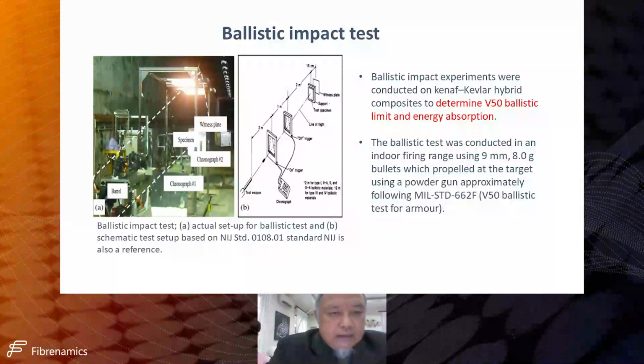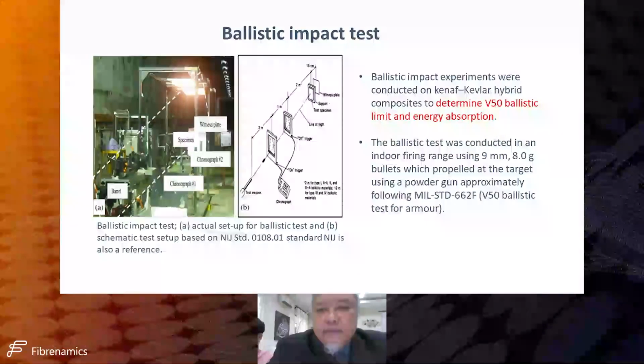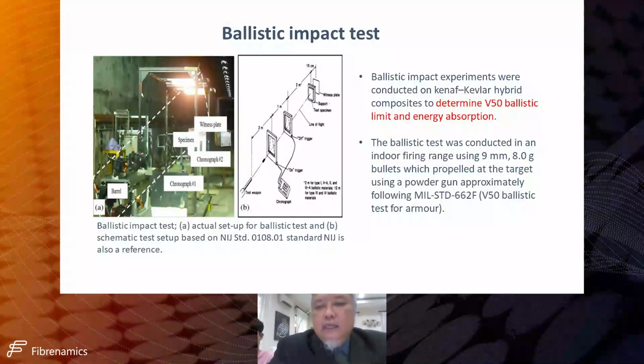The left-hand side is the actual setup for the ballistic test, and B is the schematic test setup based on the NIJ standard, the standard that is used for the ballistic impact test. The ballistic test was conducted at an indoor firing range with a 9 millimeter, 8 gram bullet, which was propelled at the target using a powder gun, approximately following the standard for ballistic test for armor.